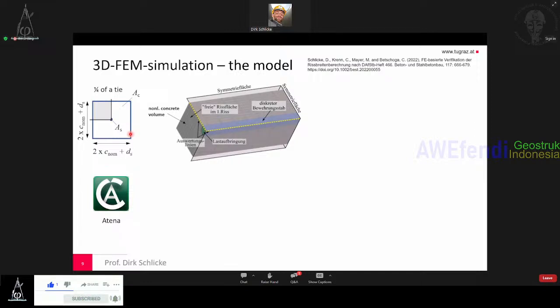We have there some nonlinear concrete volume. There are symmetry areas, using symmetry in 3 directions. We have a discrete reinforcement bar here in blue. We have a free surface for the first crack. So the first crack was not occurring due to fracture. It was already included in the model as a free surface.